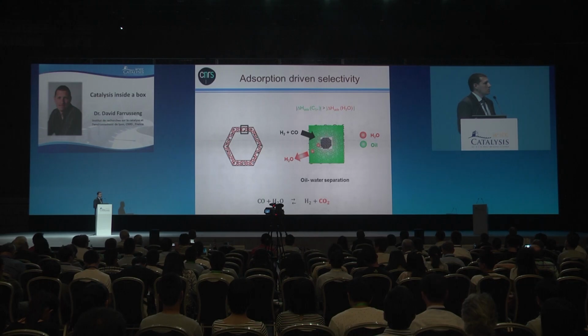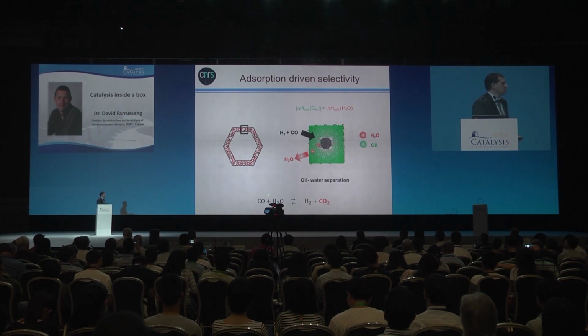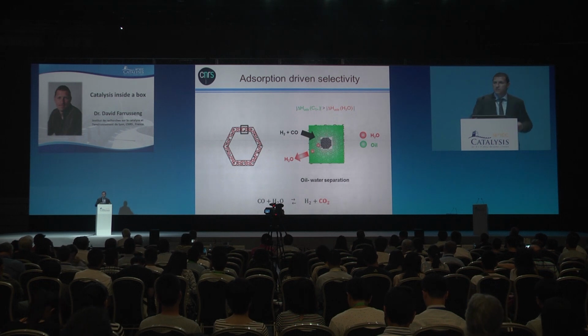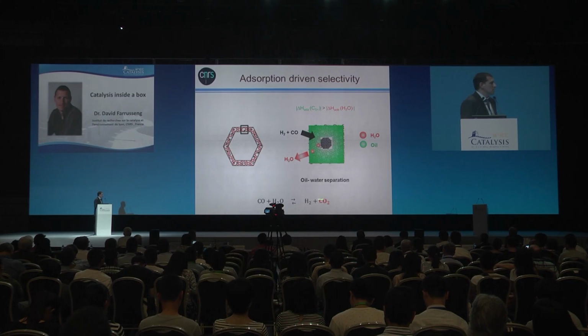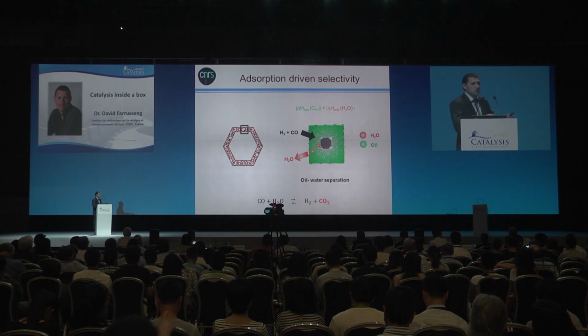We have oil and water separation, and this is why I think this reaction does not happen, or happens with very slow kinetics, because we don't have water close to the iron particle because of the thermodynamics at the local stage. This reaction, or its kinetics, is very much prevented.